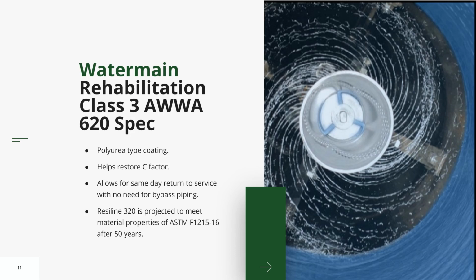What you would do is put in a composite product so that your CIPP will augment the strength of the existing pipe, or if it was just a case that the existing pipe was leaking, you put in the CIPP pipe to stop the leaks, but you're depending on the existing pipe for the structure. In this case here, there is really no structure from this product here. It is a polyurea that you're putting in here. It is a coating that is going on.